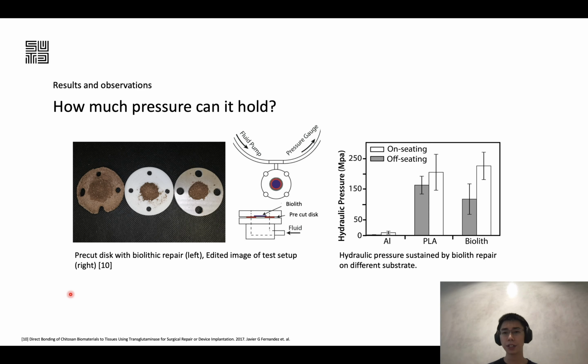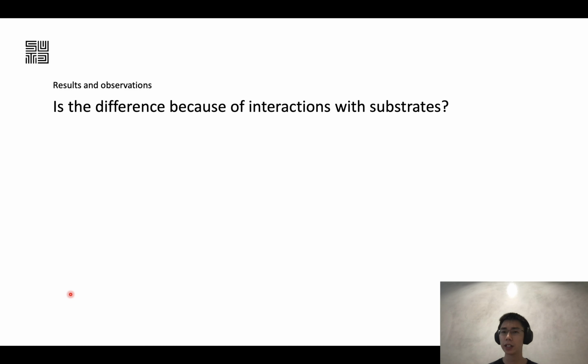And the result is this, that we see that they are able to sustain a pressure of at least 100 megapascal in off-seating condition. And this is useful because this is higher than the atmospheric pressure that we have on Earth, or even in a lunar lander cabin pressure. This means that if we have water-containing volumes in these environments and they are leaking, we can use this material to patch them up, and they should be able to hold liquid in those volumes. Now, one very interesting observation here is that the repair on aluminum substrate seems to be a lot lower than the repair on PLA substrate. And that leads us to this question. Why is that so? Is that an interaction between the Biolith and a different type of substrate?